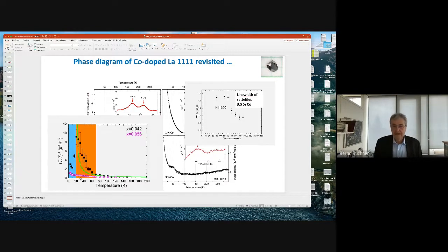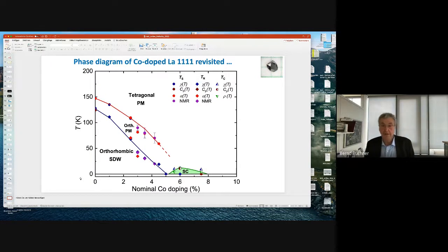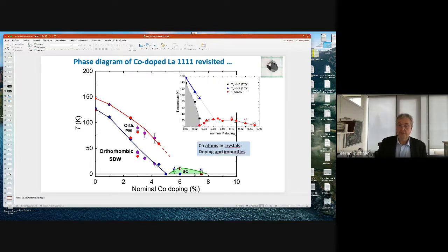So taking all these data, we end up with this phase diagram here. We have a lot of different probes. We have susceptibility, specific heat, thermal expansion, NMR, transport measurements. And then you see this is the nematic phase transition, this is the magnetic phase transition, and this is the superconducting dome. And this, of course, is much smaller here. Tc is smaller, and the dome is smaller, and these are the cobalt atoms. These are the impurities. Okay, let's say this is the price we have to pay in order to do these experiments on the crystals.